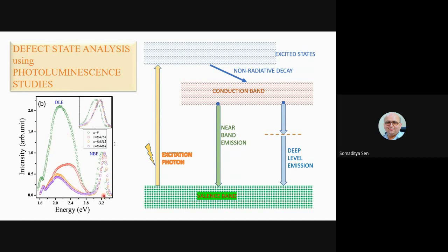These are the near band emissions, and you can see just by doping, I think this was aluminum doped. Yes, this was aluminum doped. So you have suppressed the emission here, and it is much suppressed here, and then you have a different type of blue emission at this point. So this all depends on how much the defect levels are being modified.